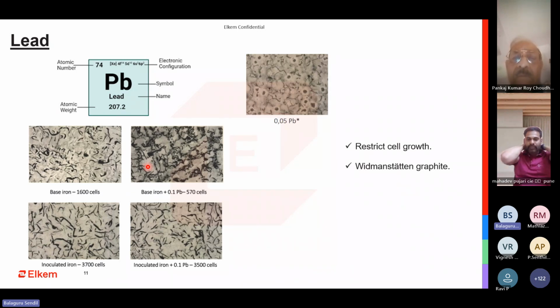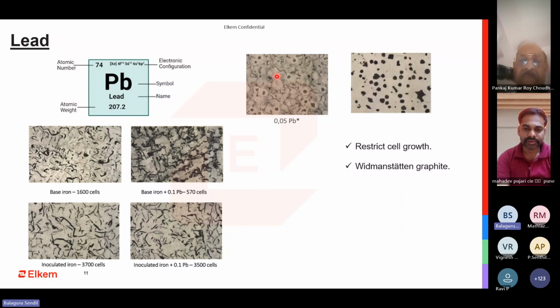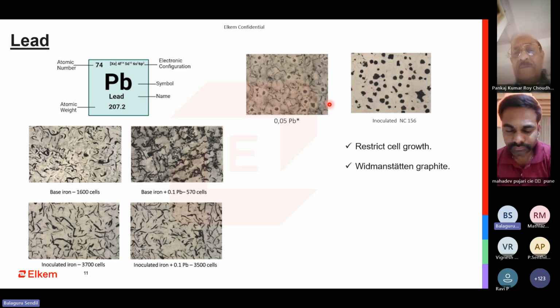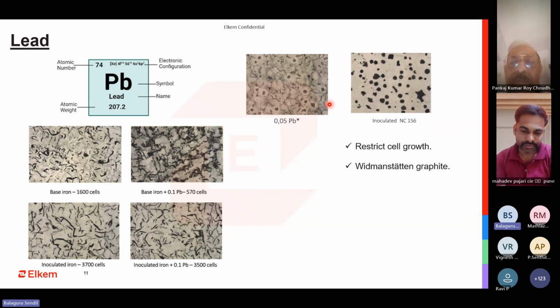Now I go to the world of ductile iron. This is a normal ductile iron microstructure before inoculation, after nodularization, that is after magnesium treatment, before adding any inoculant. If I had 0.05% of lead, I would see this sort of microstructure. You can see very thick, spiky flakes. And then I do an inoculation for it. I achieve a nodule count of 156. I'm not going to say which inoculant and which product. This is the condition that we are going to compare against. So the base is the same, the rest is comparable.